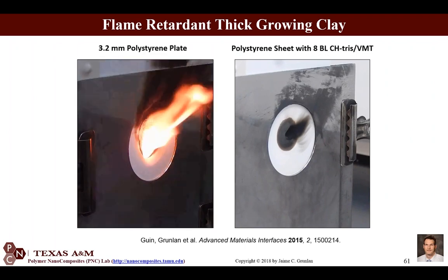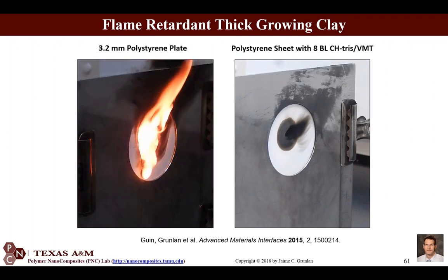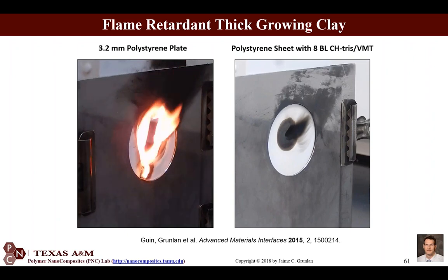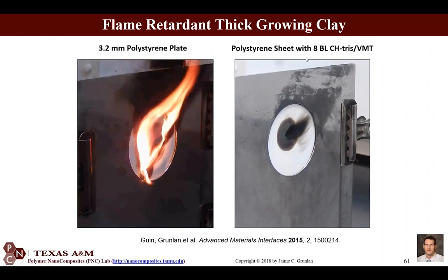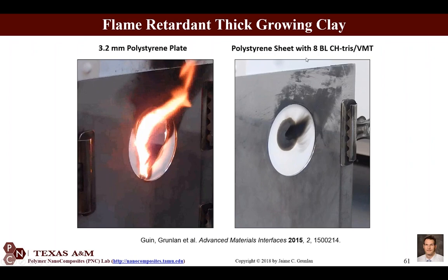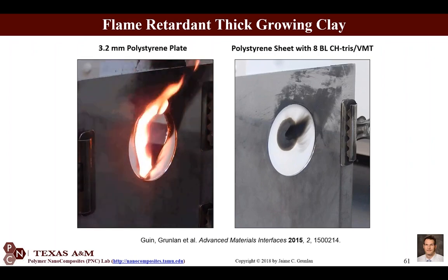The polystyrene with no coating on it, of course, is highly flammable, and it'll completely burn up. That 8 bilayer coating was 4 microns. It's a negligible thickness. You couldn't even measure the weight gain on that plate. And yet I can hold a torch there for 15 minutes and not burn through that very flammable polystyrene sheet. So that highlights some of the fire resistance things we can do as well.